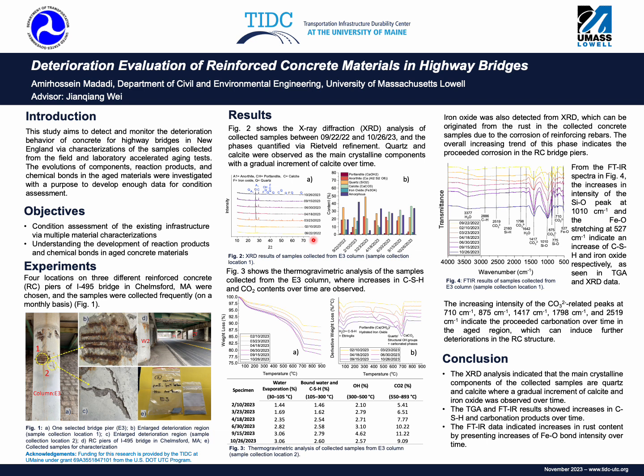The results of thermogravimetric analysis or TGA are also shown in figure 3. TGA is a powerful technique for the measurement of thermal stability of materials. In this method, changes in the weight of a specimen are measured while the temperature of the sample is increased. Figure 3, part A shows the weight drops at different temperatures, and part B indicates the first derivative of the TGA curve, in order to better understand the decomposition patterns, and the table below provides the quantification data of the different phases. Based on these results, the main findings indicate increases in CSH, or calcium silicate hydrates, and also the CO2 content of the samples over time, which shows the ongoing reaction within the concrete materials of the bridge piers.